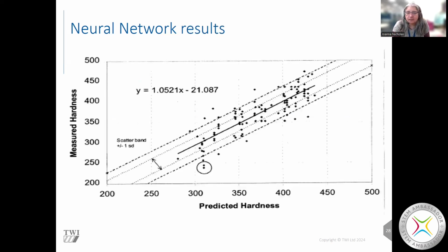The neural network results were similar to that for the empirical model. We had pretty good one-to-one correlation. Again, standard deviation of around 25. This one was slightly less, 24 rather than 25, but standard deviation of around 25. And the neural network model could be used, but we had to put some boundaries around it, because just like for the empirical model, I would say don't use it outside of the test data.